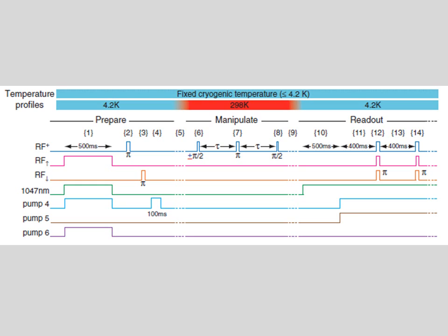The researchers' results show that the temperature manipulation does come at a price. In this case, only about 62% of spin coherence remains after the temperature cycle, which is equivalent to a state fidelity of 81%. But this is certainly better than the loss of all coherence, which might otherwise be expected from quantum systems which operate only at cryogenic temperatures.